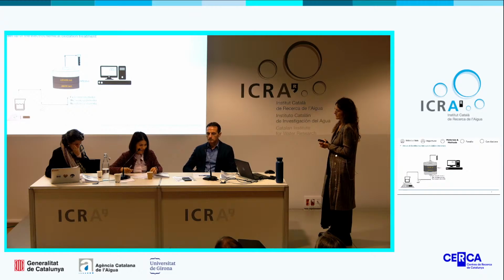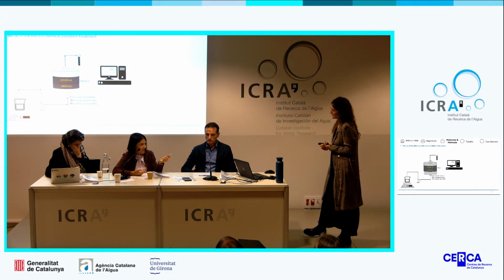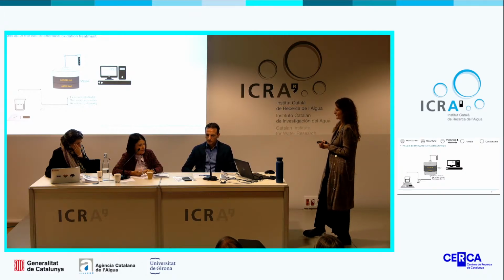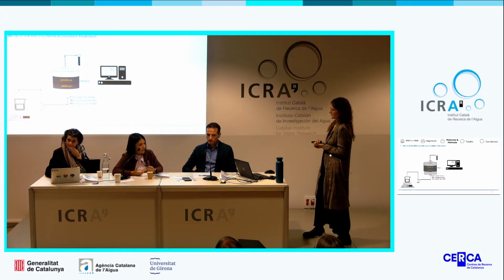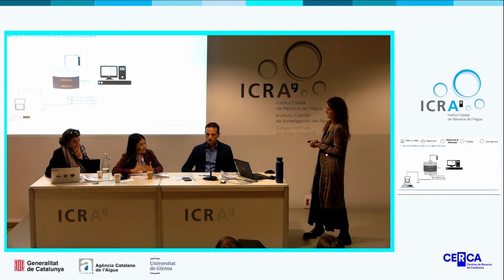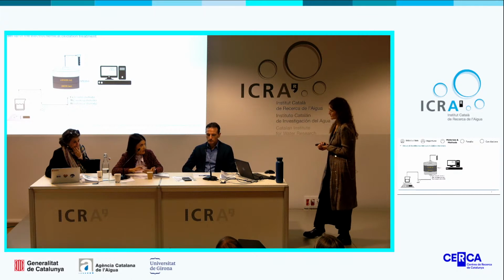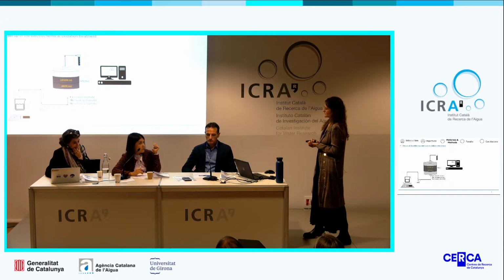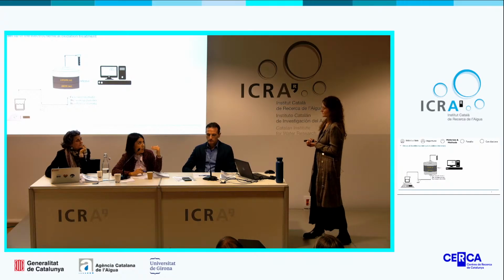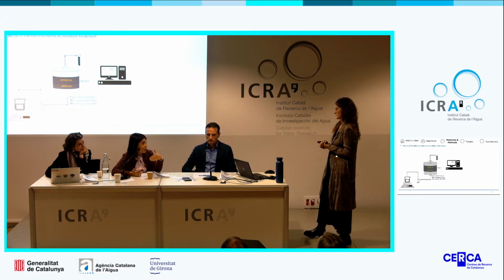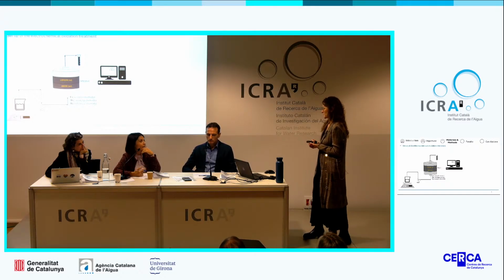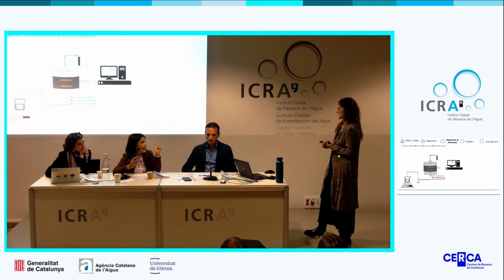Regarding bacteria, I also have some doubts about the role of the oxidant. Have you run any experiment without bacteria just to check the real concentration of oxidant that you are able to generate in your system? Because the concentrations that you give in your tables correspond with the oxidant that remains in the system after the treatment, the oxidant that has not reacted with your pollutants. Have you run any kind of blank test just to check the concentration of oxidant that your electrodes are able to generate?